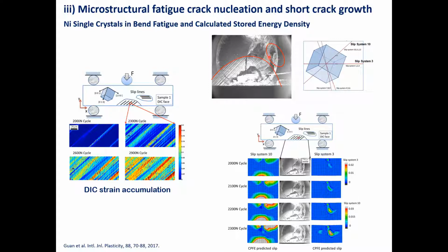We also see a region in the sort of mid region of the sample in there schematically, where we see another slip system activated, this time slip system 3, which is horizontal. It's where the shear in the beam is maximum. So we do see these two differing slip systems activated and with very defined ranges over which they are activated.